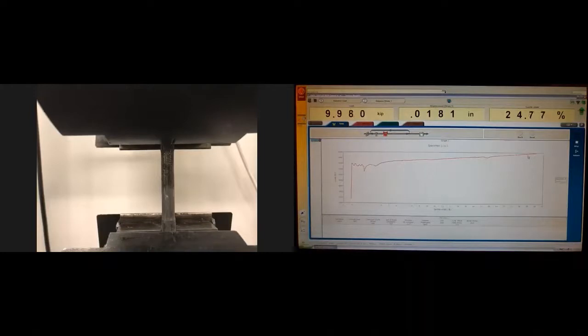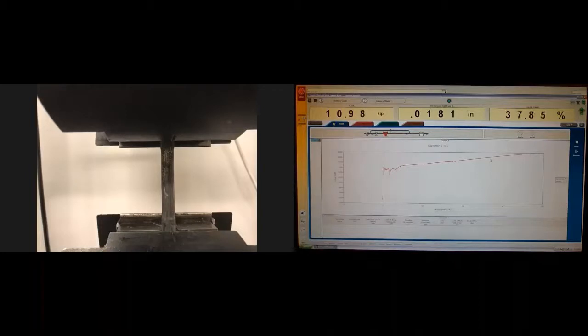dislocation movement. And dislocations start to pile up, and they will, at some point, exhaust all this strain hardening capacity that's going on right now. And this strain hardening capacity is being exhausted more and more, until we reach the maximum force that this material can handle. And this is still a homogeneous deformation. So the sample is being elongated and contracted evenly in every point within the volume of this middle section, at least, of the sample.